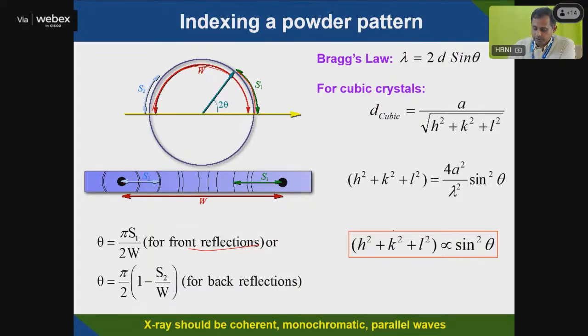Then by using Bragg's law, n lambda equals 2d sine theta, if you get theta here, you can find out everything. For a cubic system, d equals a by root of h square plus k square plus l square. So h square plus k square plus l square equals 4a square by lambda square times sine square theta. So h square plus k square plus l square is proportional to sine square theta.